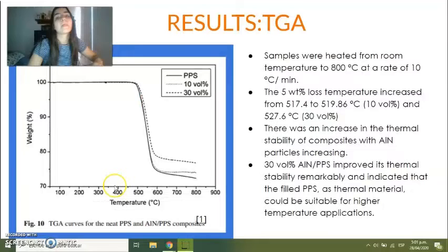The crystallinity of the PPS increased with higher aluminum nitride content at first, and decreased when the content of the aluminum nitride was over 15 volume percent, because of the aluminum nitride's heterogeneous nucleation effect on the PPS.